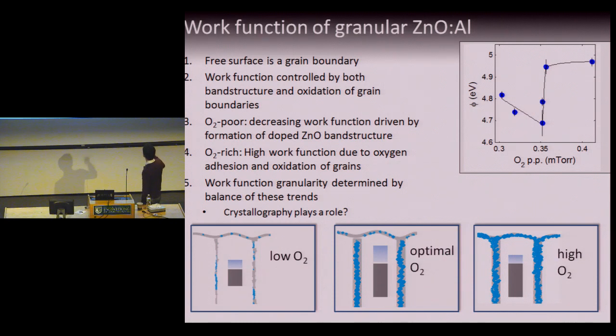And finally, if you really aggressively oxidize this material, which we can explicitly show by post-processing annealing and the UV ozone environment, you get to the point where there are oxygen defects uniformly populated across the front face of the surface. And you reach a situation where, again, you have very little contrast in the work function as you scan across the sample with a scanning probe tip.